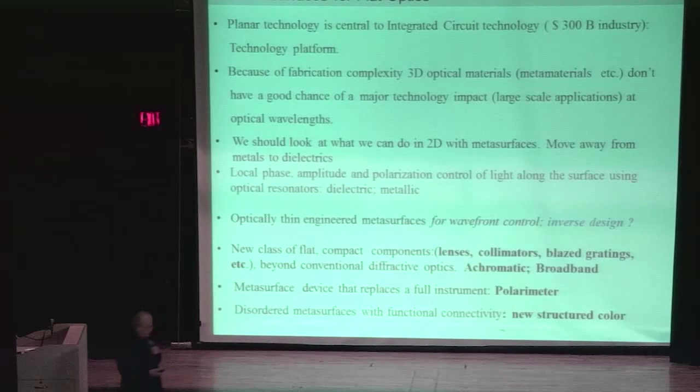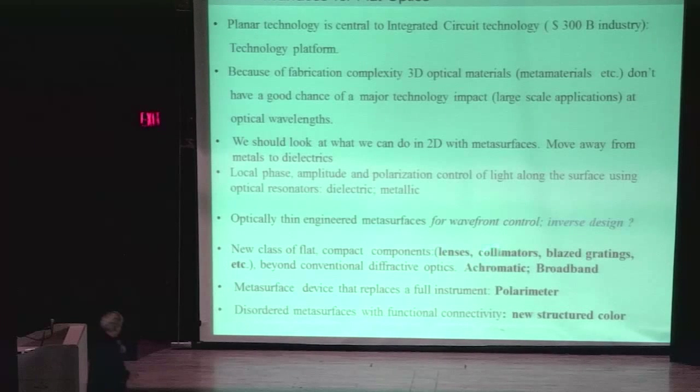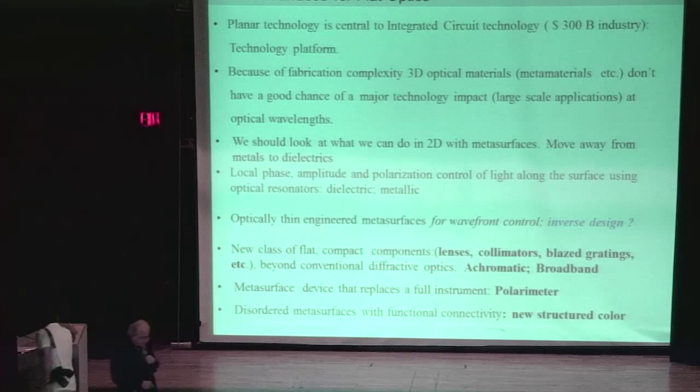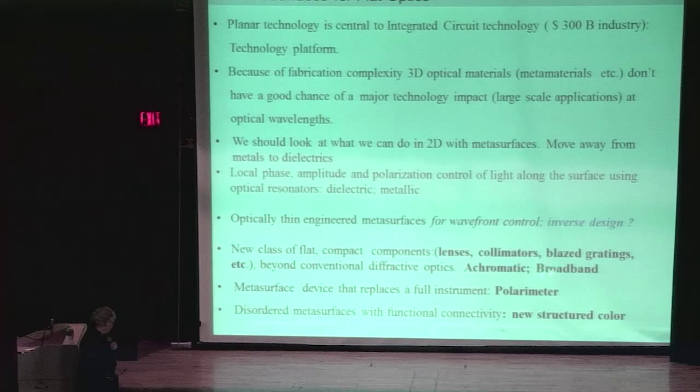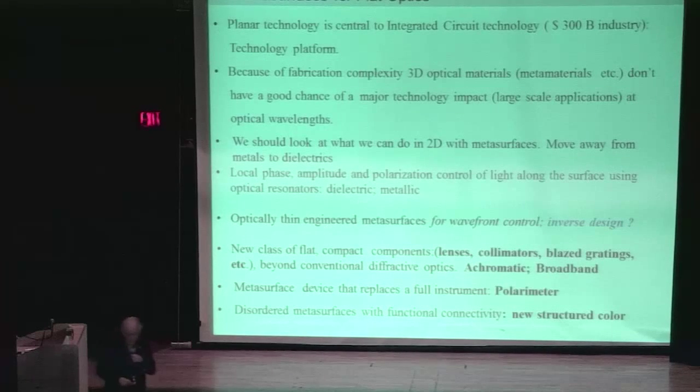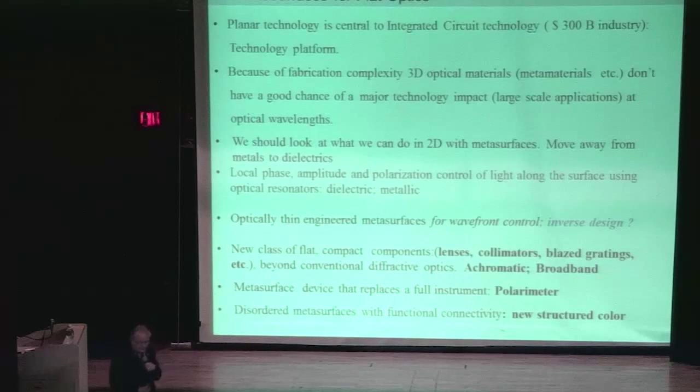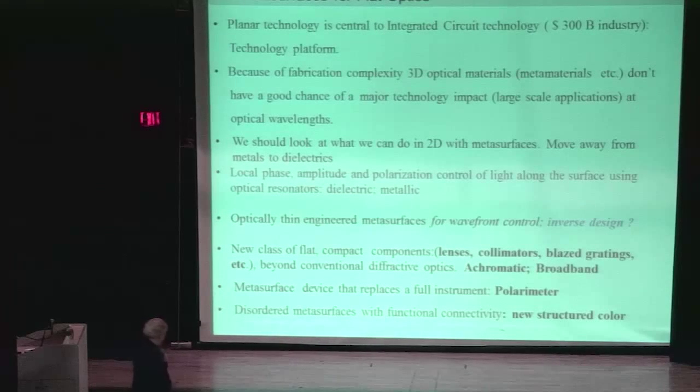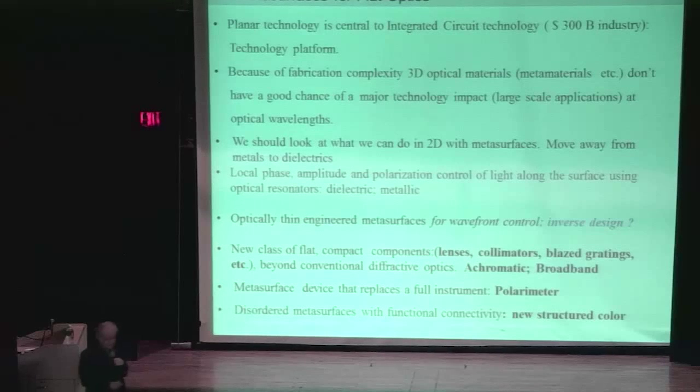So I think there is much more future from a technology point of view if we planarize metamaterials, turn them into metasurfaces, and then it's all about the local control of the phase, the amplitude, the polarization. And we are moving, all the groups working, from metallic type structures to dielectric structures. So essentially we have to design wavefront control. An interesting point in the future is to do inverse design, to design them really efficiently. So you give me a wavefront and I can actually design the metasurfaces that creates a particular wavefront. I will talk about the work my group has been doing on some of these flat components: lenses, collimators, blazed gratings, and particularly addressing the issue of aberration. Can we make them really achromatic, which is important, like lenses?